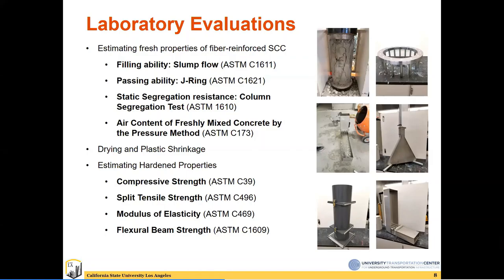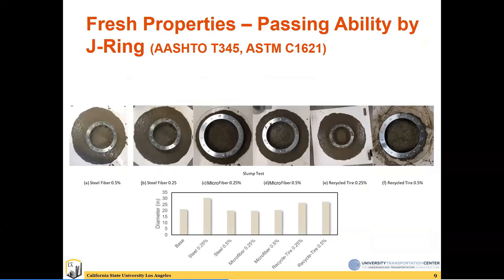For hardened properties, we are basically using the four basic hardened properties, including the compressive strength, split tensile strength, modulus of elasticity, and also flexure beam strengths. This last one is specifically designed for fiber reinforced concrete mixes, and we are going to see how the fibers, specifically recycled fibers, can enhance the properties of the mix.